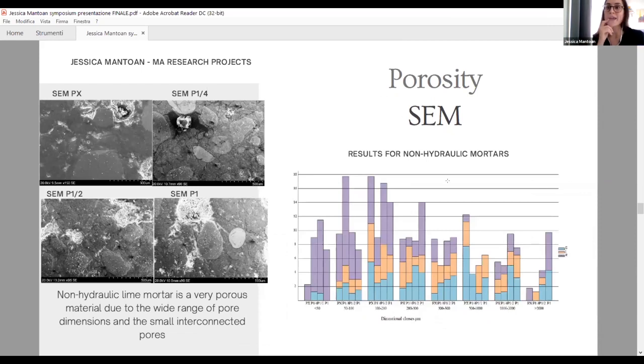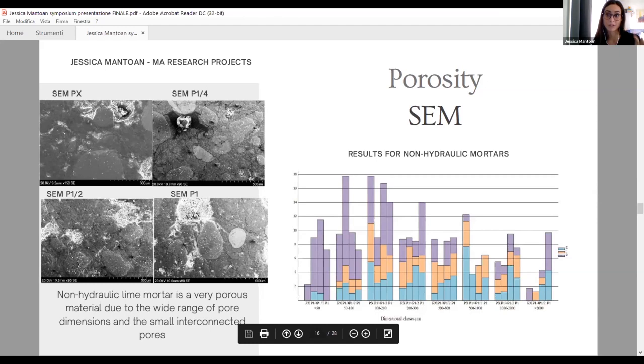The same study was made for non-hydraulic mortar, and quite surprisingly, the results are completely different with respect to hydraulic mortar. In this case, we can see that the use of barium hydroxide increased terribly the amount of capillaries. So we can see that mortar without barium hydroxide has a quite reduced quantity of capillaries, while the mortar containing barium hydroxide has many more capillaries. But even more interesting are the changes in the really, really large pores, where mortar containing really large quantities of barium hydroxide presents a huge amount of really, really large pores.